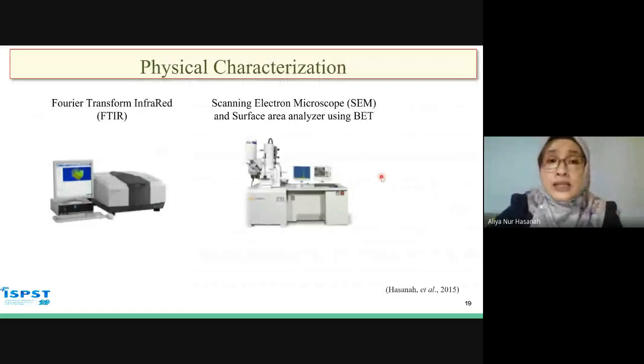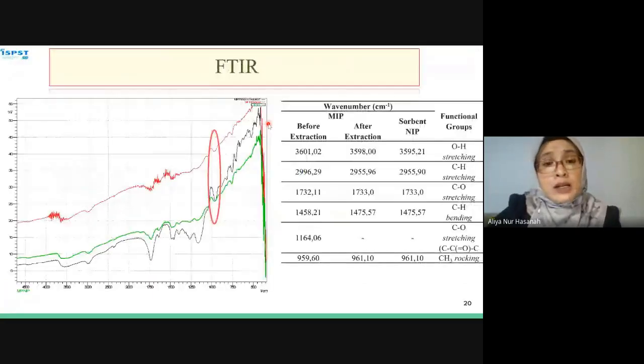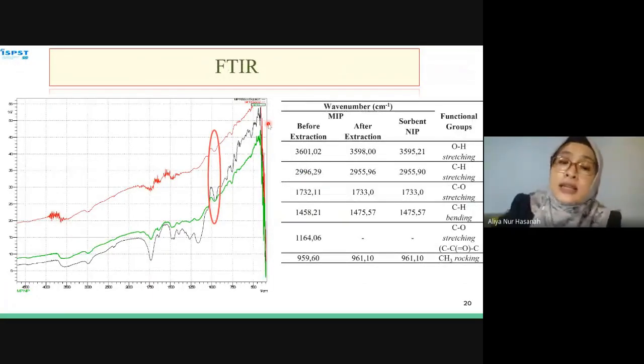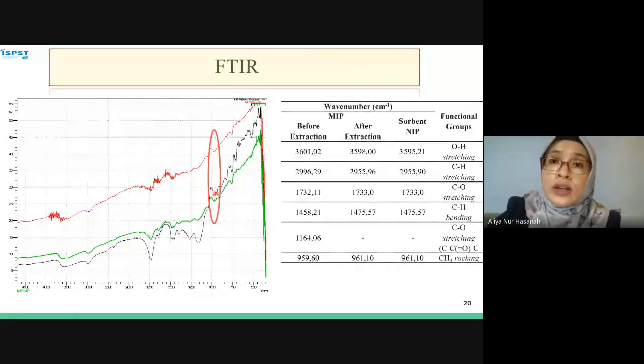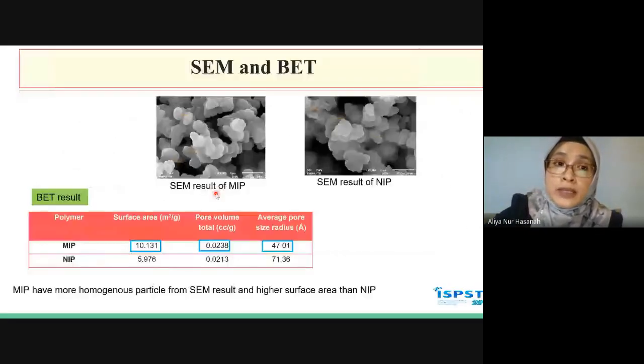After we analyze the analytical performance, our next step is physical characterization using Fourier transform infrared, scanning electron microscope, and also BET for surface area analysis. In the FTIR result, we can see no peak at wave number 900, no double peak at wave numbers 900 to 1000 per centimeter. So it means we don't have any vinyl group that correlates with uncompleted polymerization. So our polymerization is already complete.